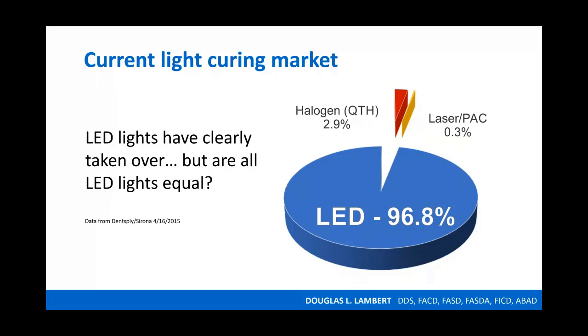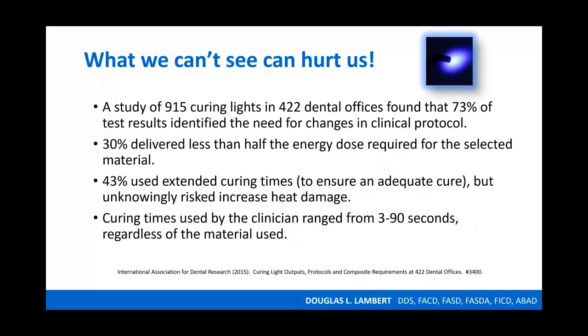But is an LED light an LED light? Are all LED lights equal? What we can't see can hurt us sometimes, and this is an interesting study of over 900 curing lights in over 400 dental offices. And they found that 73% of the test results identify the need for changes in the clinical protocol of that dental office. 30% of the lights delivered less than half the energy dose necessary for the selected composite material.